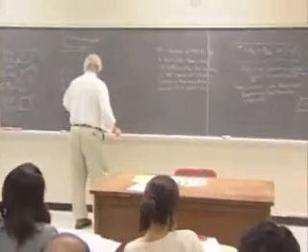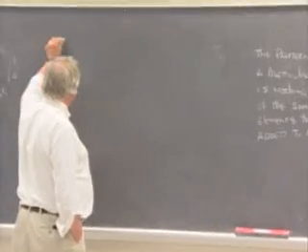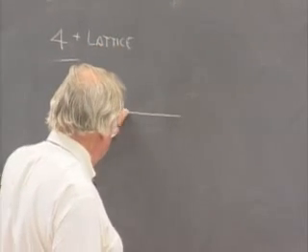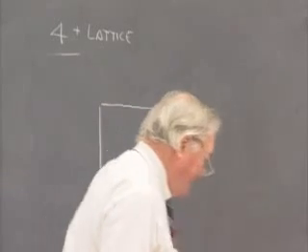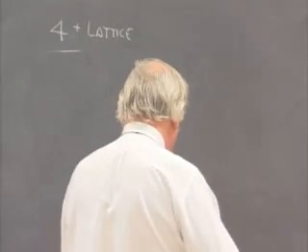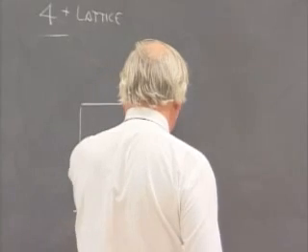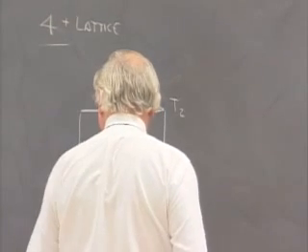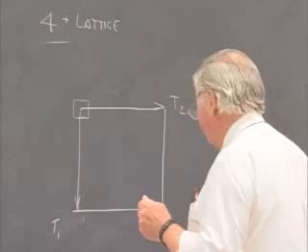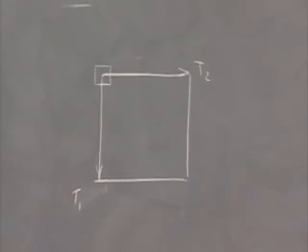Let me do, in the couple minutes remaining, let me make one more addition just to show you how things change when you add a rotation axis that has more than one rotation operation. Let me ask what happens when you add a fourfold axis to a lattice. We've seen that a fourfold axis can coexist with no lattice other than one which is dimensionally square and which has the same thing hanging about two translations that are exactly 90 degrees apart. So what we're doing is taking a fourfold axis and dropping it in at the corner lattice point and then stepping back before all hell breaks loose.